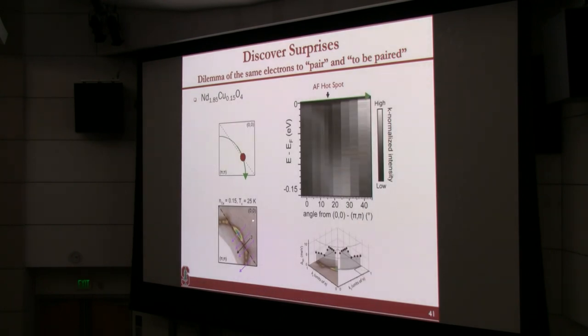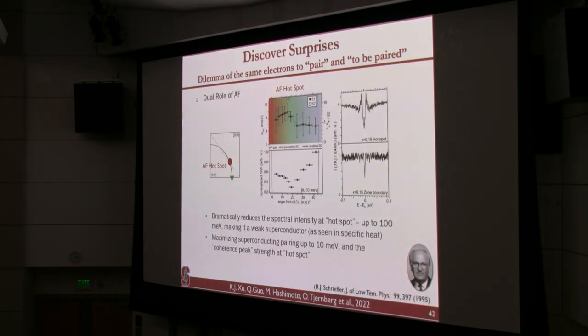Now with that, I come back to this, and I hope you now see this shadow is really the superconductivity and shows a maximum in this region near the hotspot, meaning that it's the most deviated from the Fermi level zero. At the same time, you see the spectral weight in this region also suppressed the most. So in a sense, whatever the interaction is here, it gives you a maximum of superconductivity in this region, and at the same time also takes out the density of states you need to promote superconductivity.